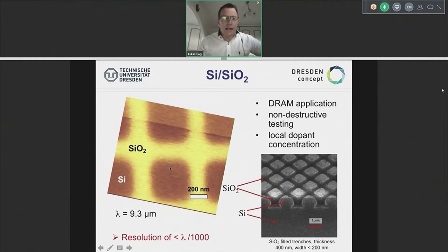So we did that actually with this kind of near-field optics using a wavelength of 9.3 microns of a CO2 laser, and the result is shown here. You see brightly the SiO2 with a very good resolution, and you see the silicon in black simply because the silicon dioxide is resonant at this wavelength. So we can say that we can probe any material for its resonant absorption, and hence with a resolution again way below the diffraction limit, in that case lambda over 1000.